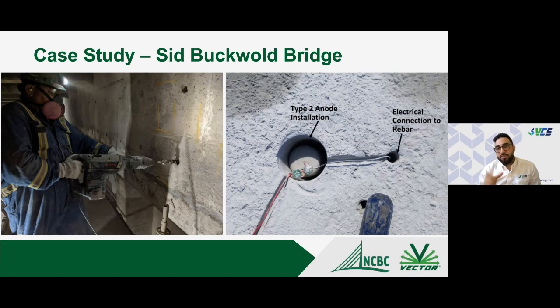they are controlled. The battery inside of them is controlled. So there's almost no interference between galvanics and the type 2 anodes. However, if you're using a full ICCP system that uses noble anodes like titanium or platinum, there would be interference and you would have to account for that and take that into account when you're looking at and analyzing data from it.